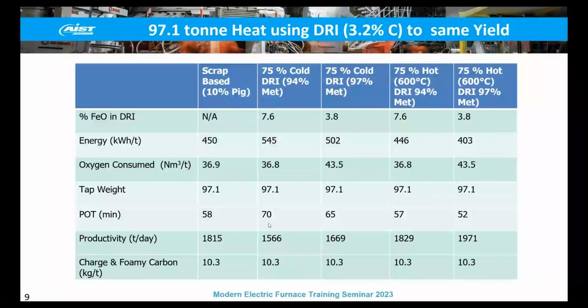You're seeing an increase in power-on time and a decrease in productivity. You can see the same scenario, but slightly better, for cold DRI with a higher metallization. So metallization is key when looking at alternative iron units, or really any iron units you're putting into an electric arc furnace.